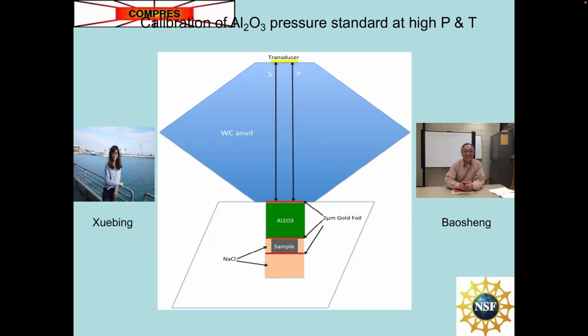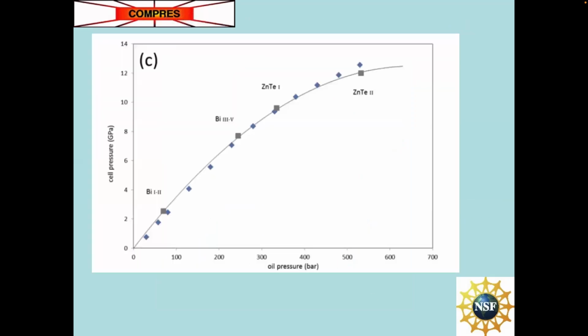I think the next slide will show some results of that work. Yes. This is cell pressure as calibrated versus oil pressure. The diamonds are the data from the alumina experiment up to 12 GPa, and you can see that they compare very well with the standard transitions that we know from previous work in bismuth and zinc telluride, so that instead of having just a few fixed points, we have a continuous measurement of pressure within the sample chamber. Next slide.